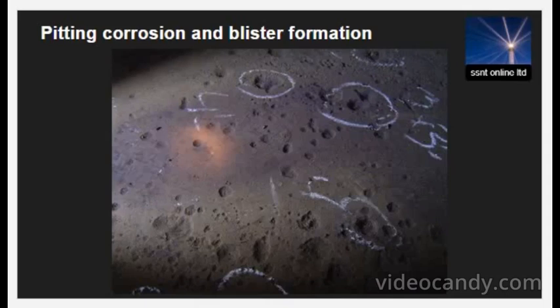Pitting corrosion is often observed in the bottom plating of ballast tanks, especially near the bell mouth, or next to suction wells associated with the submerged pumps fitted within the tanks. Pitting corrosion begins mainly with the local breakdown of the coatings, exposing the bare metal, and thereby getting accentuated by oxidation and galvanic reactions in the area.